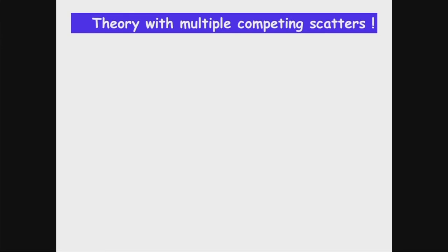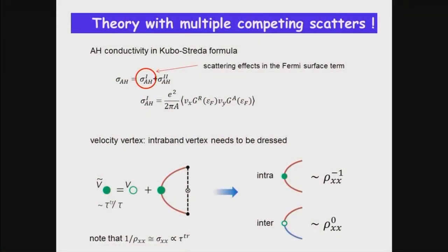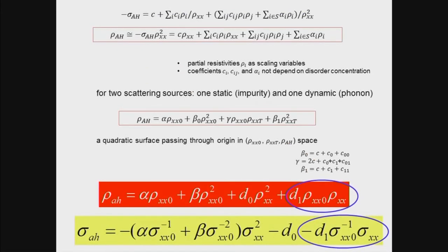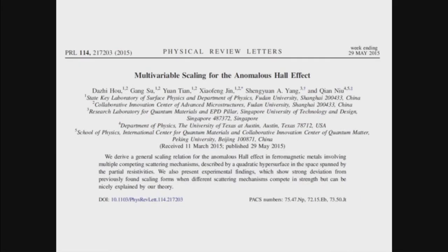So that's the theory. For the first time, you can treat the defects on equal footing, not only one, but multiple. I won't go into the detail, but then you just calculate the conductivity with the Feynman diagram. And the final theoretical result is these two lines. The three terms we phenomenologically already established, now you find the theoretical justification. It should be there. And this is a crossover term. This causes the deviation of the data. So this part turned out to be determined by this theoretical result. So we collaborated together and we found this. Five minutes, I will save some time for others.